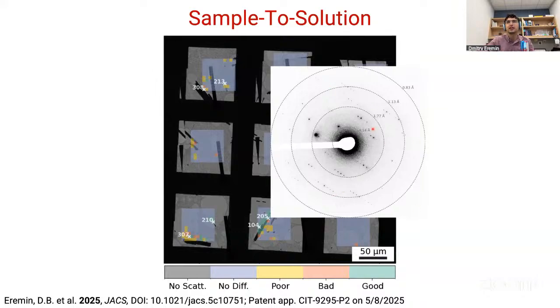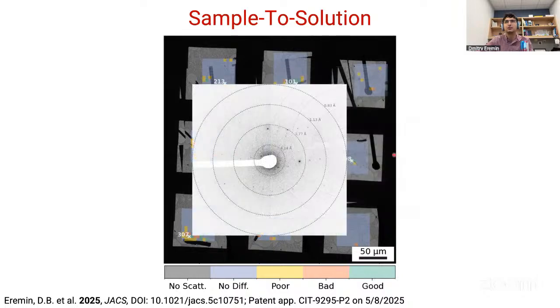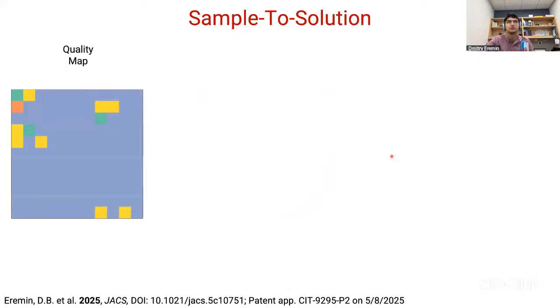So maybe in this particular case, the diffraction quality index was not as high as in the previous one, but it's still a pretty good diffraction pattern. So all the targets that are based on the number of diffraction peaks are still going to go in. And the same will be for the intensity. So maybe very bright diffraction peaks might be something that you can look for in this particular structure. And with solved structures, we've solved structures from all 3 types of data. And that's why we think that it is important to have a less biased acquisition pipeline.